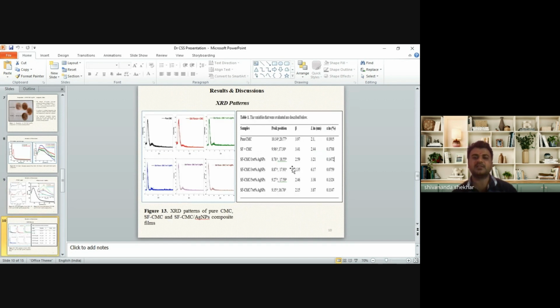Then we have done the XRD patterns. We can observe here a semi-crystalline peak appeared. This is the presence of the pure carboxymethylcellulose, because it is an amorphous material, and another small broad peak you can expect here. So this is also silk fibroin. This peak is due to the silk fibroin. Again in the composites, a small peak appeared. It is not visible clearly, but this is the presence of AgNPs in the matrix.